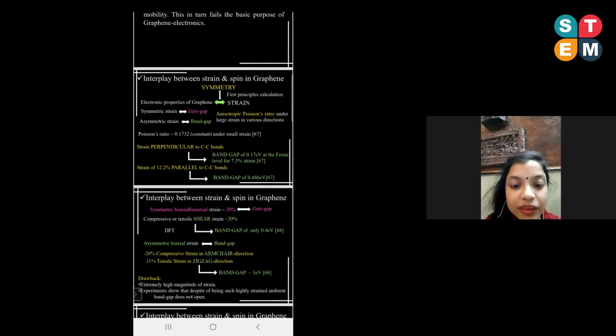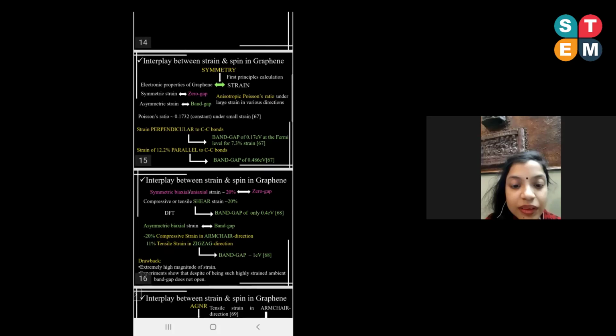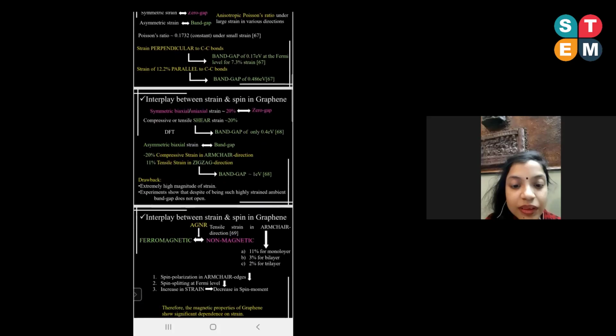Now, if the strain is applied in a direction perpendicular to the carbon-carbon bonds, then a band gap of 0.17 electron volt opens up at the Fermi level, but the magnitude of the strain has to be 7.3%. And for a strain of 12.2% parallel to the carbon-carbon bonds, a band gap of only 0.486 electron volt opens up. So we find that there is an interplay between strain and spin in graphene.